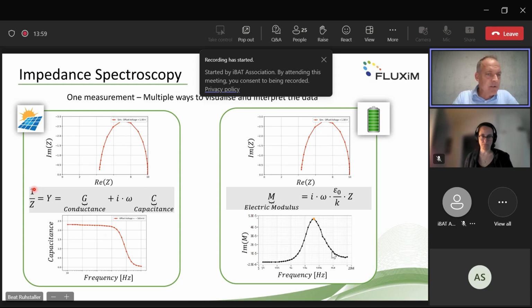And as I just introduced, this is the admittance. And this admittance can be split into conductance and the capacitance with this prefactor of omega. This is how we usually post-process the measured data in the field of PV or OLED. And in the battery research community, we have seen that an alternative way of expressing this impedance is the use of the electric modulus, and then look at for instance, the imaginary part of this quantity M, and then study this resonance phenomena here. But basically, it's just the same methodology, but it's plotted in a different way.